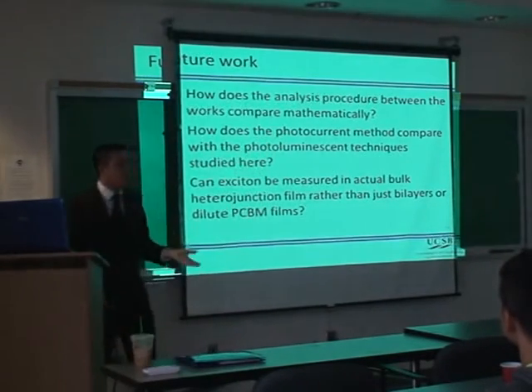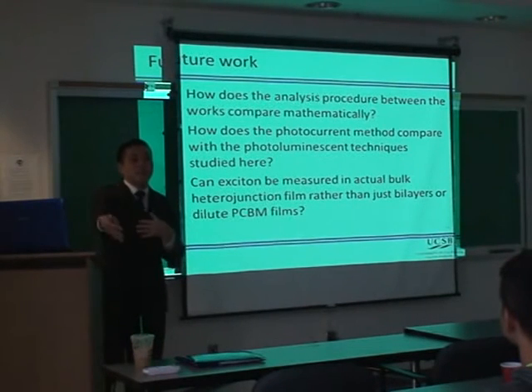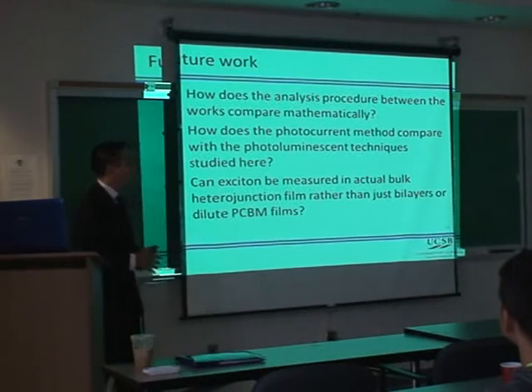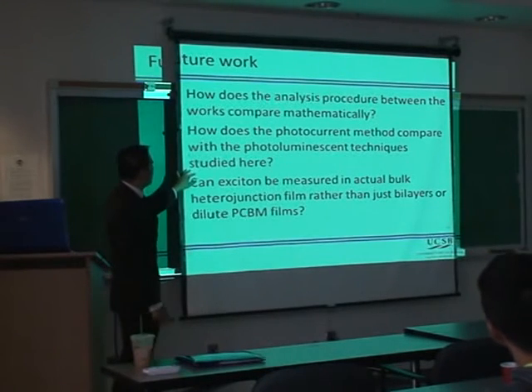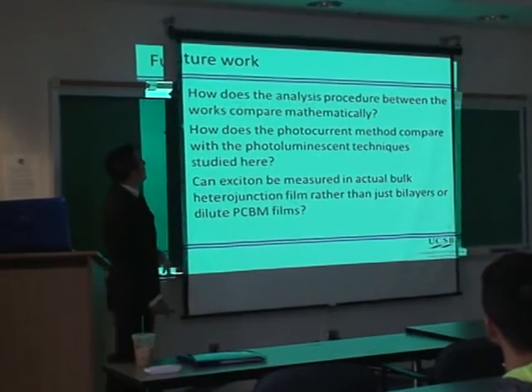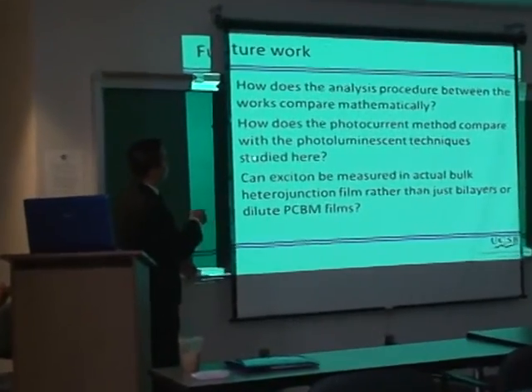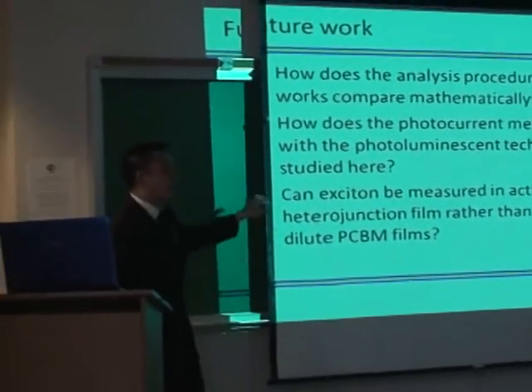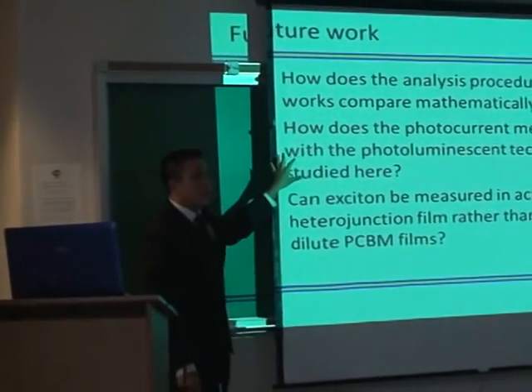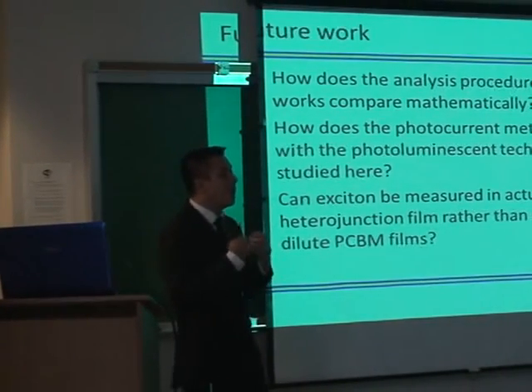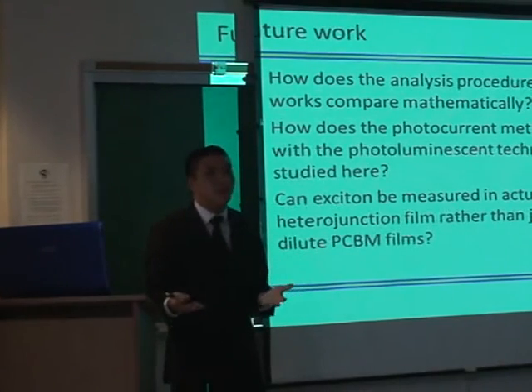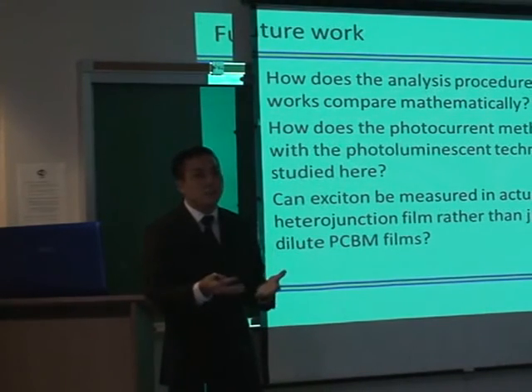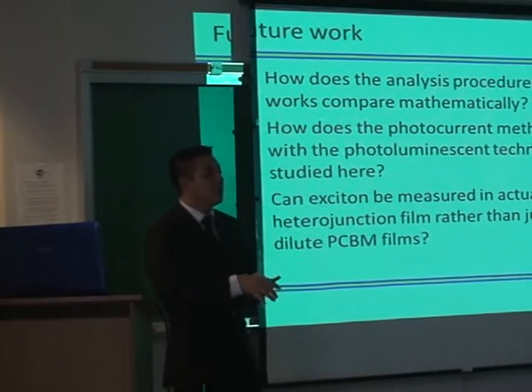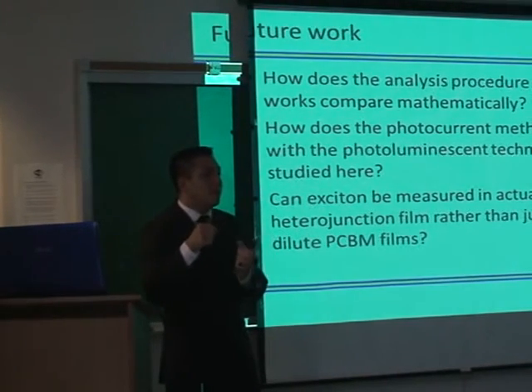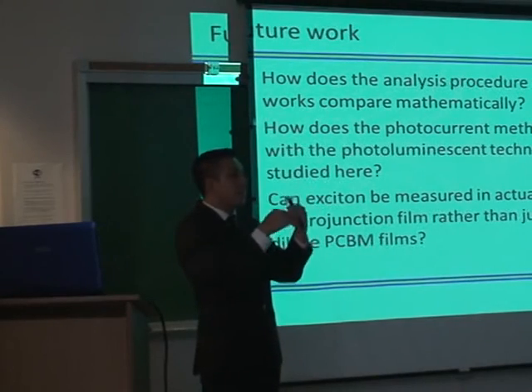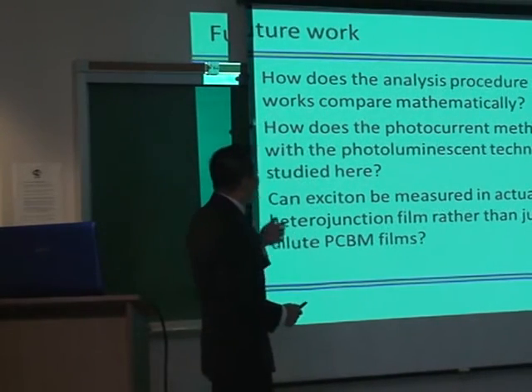And some of the preliminary results show that some techniques overestimate the diffusion coefficient compared to others, just based on mathematical calculations. Another question I might ask is, how does the photocurrent method compare with the photoluminescence techniques? All the techniques I studied in this specific work were for materials which are able to emit light. But there are a lot of materials that aren't able to emit light. And for those materials, the way to still calculate the exciton diffusion length is to measure the current, because the more excitons that reach that interface, the more current you would generate. So you can calculate it that way too.